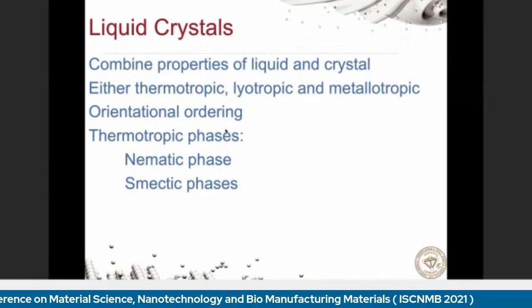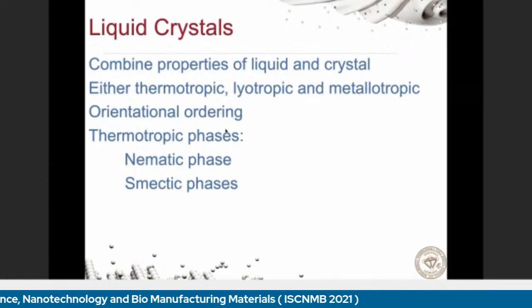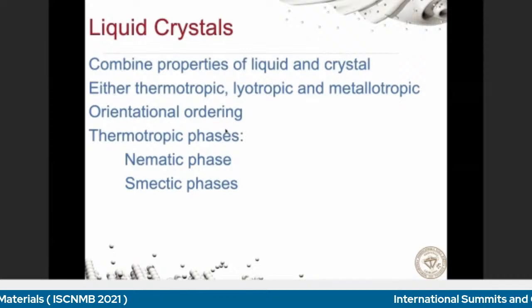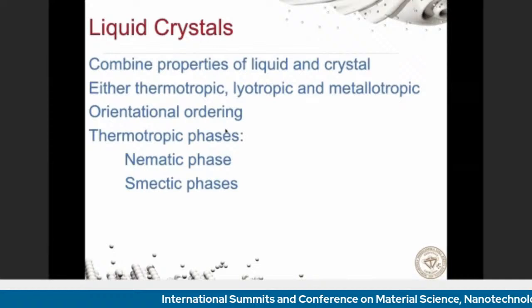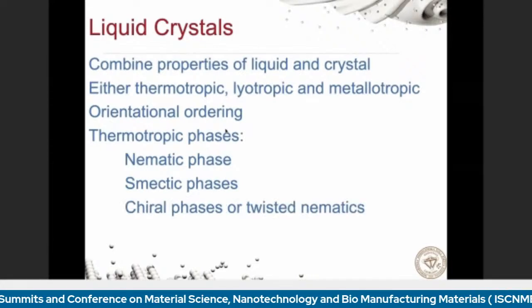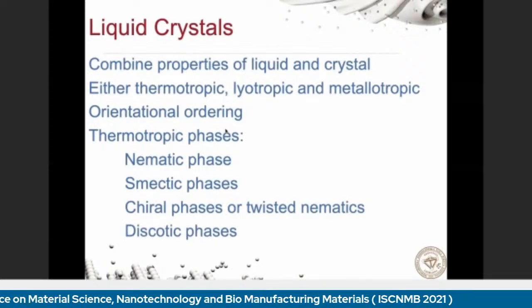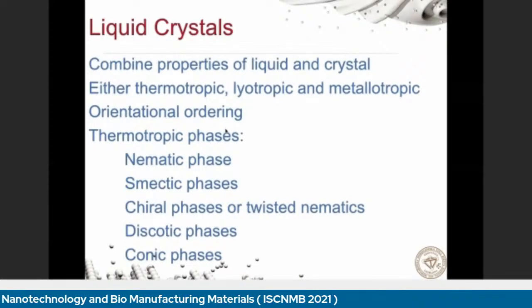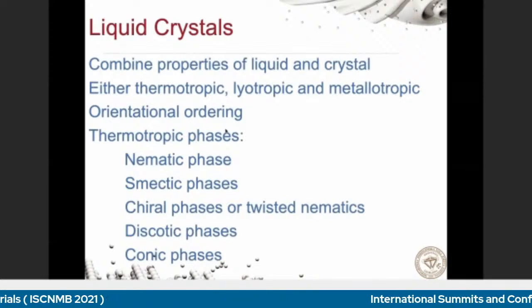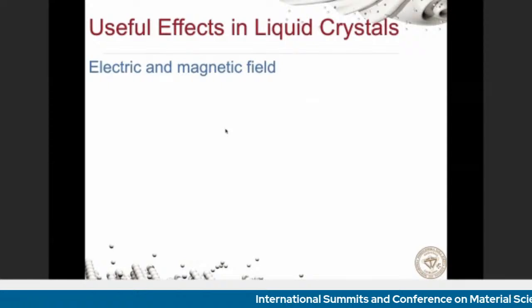So small angle X-ray scattering was actually the method of choice that we use for observing smectic phases in the liquid crystals. And you can really see very precisely both the layer distance, the order parameter, and also the uniformity and the correlation length. Then there are other phases, of course, chiral, twisted, discotic, and conic. And among these phases, most of our work has been actually focused on nematic phases and on the smectic phases.